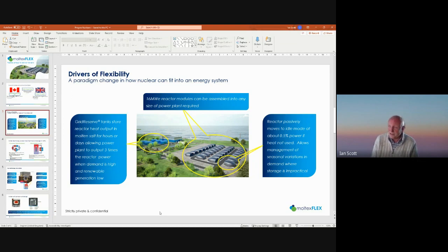And the third source of flexibility is that this reactor, which I will describe in the next slide, entirely passively goes from full power down to what we call idle mode of about 0.5% of its full power, with no operator action at all. So it is an intrinsically flexible reactor. That is not something you would ever dare do with a solid fueled reactor, because the iodine problem would cause you very severe problems.